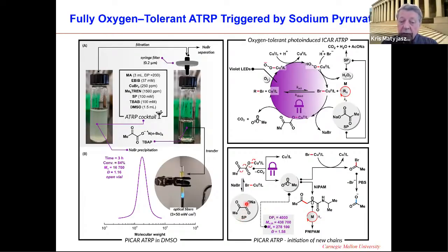So here it is shown again that you have a sodium pyruvate in the presence of copper-2, you generate the corresponding copper pyruvate 2 species, which then after irradiation produce copper-1 and this acetyl radical. Acetyl radical can also take bromide from the copper-2 species, reduce it to copper-1, and form the acyl bromides, which in the aqueous system, they are very hydrolytically unstable and generate acetate anions, or a small amount of them can initiate polymerization. So we cannot go to molar masses in this system in a range of 1 million or so, because there would be small amount of new chains from these acetyl radicals. We are now working on how we can potentially improve selectivity in this reaction.